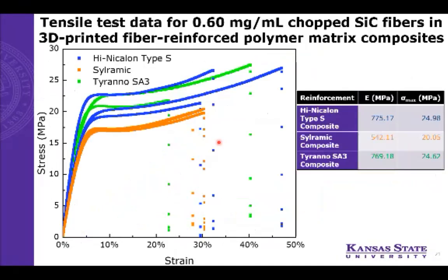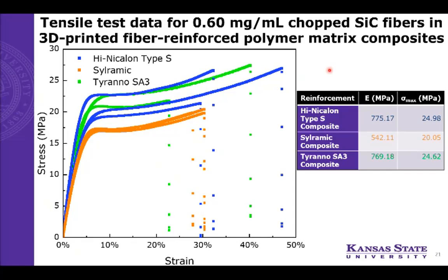We also performed some initial testing with 3D printing, where we tried to chop up the silicon carbide fibers at 0.60 milligram per milliliter concentrations and distribute them throughout a photopolymer matrix before 3D printing composites. We'd like to continue working on that and get a more consistent procedure and data going. But this is what our initial experiments show. From that, we can see the Hi-Nicalon Type S followed by the Tyranno SA3, and then finally the Sylramic composite as far as the order, which follows along with what our continuous fiber epoxy resin composites were showing.